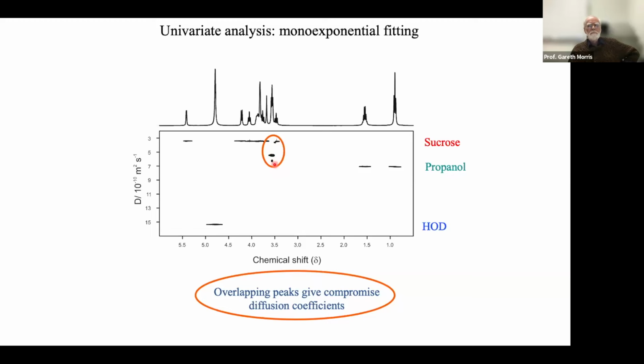And an experienced DOSY spectroscopist faced with that sucrose, propanol, HOD spectrum I started with, would look at it and say, oh yes, those peaks that are scattered around, apparent diffusion coefficients intermediate between those of the three solutes, are arising just because of overlap. And then you go on to do the PSYCHE-iDOSY pure shift experiment, and sure enough, they line up nicely. So overlapping peaks give us compromised diffusion coefficients.